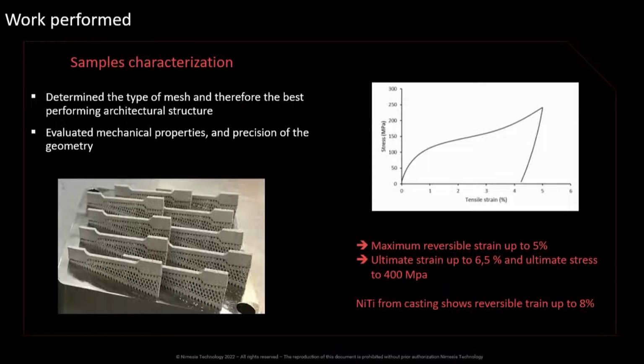Okay, so the second step was to create samples and to perform tensile tests on the sample, and to find if we have exactly the same performance as nickel titanium from casting. So we make this small and very nice sample, and then we perform the tensile test, and this is the result that we had, which is quite good. I mean, it's encouraging because we can reach reversible strain up to 5%. And from casting, nickel titanium can have a reversible strain up to 8%. So, okay, it's not 8%, it's 5%, but it's good.